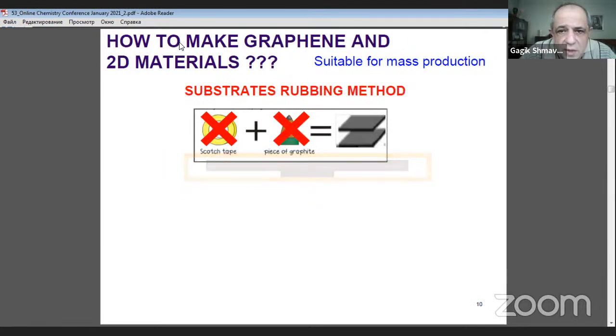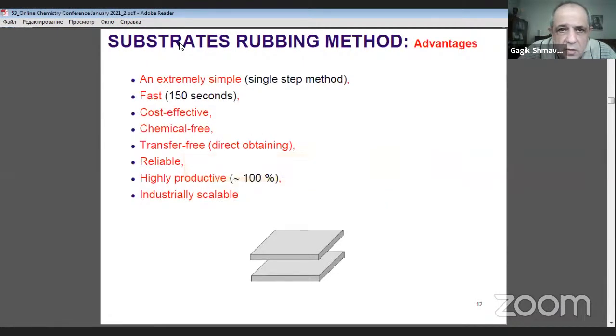So here is the substrate rubbing technology in which we decided to avoid the Scotch tape method and pencil, and instead we use two substrates. During this rubbing process, we are not using any templates, techniques, high temperature, chemicals, and sonication. And more interestingly, we can realize this rubbing process by hand. So the substrate rubbing technology is an extremely simple, fast, cost-effective, chemical-free, transfer-free, reliable, highly productive, and industry scalable method, which allows us to get unique two-dimensional atomic nanostrips.